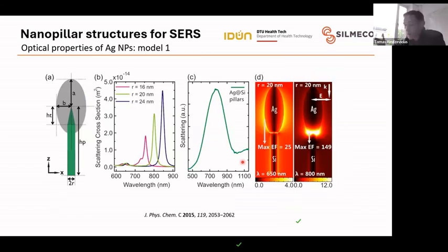And then there are a couple of ways in which we tried to model it. The first model was simply ignoring the metal film, so thinking about it like a mushroom, more or less. You have a silicon pillar and a head on top. Now this part here turned out to be very important, because in the beginning we ignored it. But when we looked closer at the SEM images, we saw that it's not really sitting on the top. The pillars are actually sharper, and then you have sort of a coating, and you have this silicon cavity kind of inside.